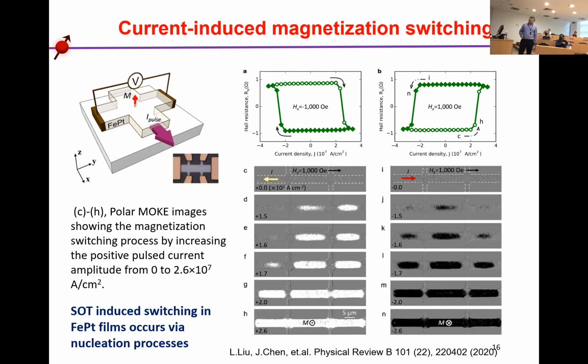And we still use the polar MOKE to visualize the domain switching in these materials. From here we can see that as the current increases, the domain starts to reverse, and as the current intensity increases further, all the domains have been reversed. When we change the current direction, the domains reverse to the other direction.